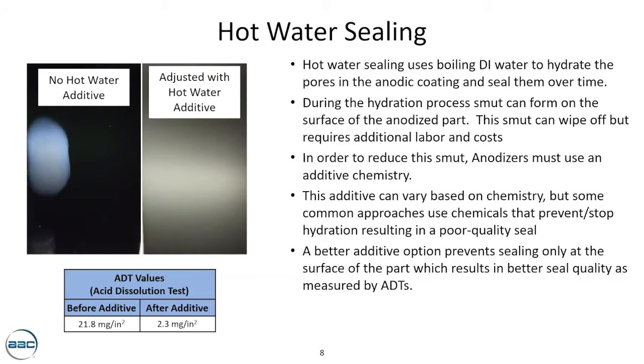Essentially what that test is telling us is a part that is sealed is put into a chrome phos bath for a certain amount of time. The weight is measured before and after that immersion. And the less weight that is lost, the better the seal. Essentially what that means is if the seal is good, less of the anodic coating will be destroyed in that bath. So what you're looking for is kind of like a golf score, a low number. So let's start off here with the hot water sealing. So you'll see two panels there.